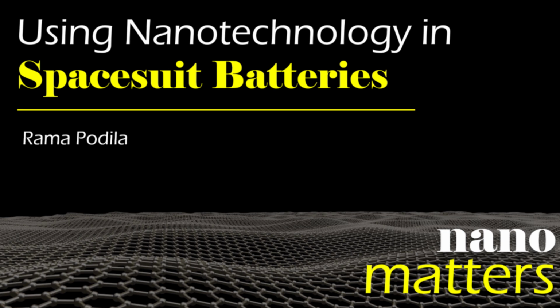So these batteries can not only pack so much power, but they're stable, because now these carbon nanotubes are interlinked between small silicon nanoparticles. So even if they are pulverized, they still fall back within this foam of carbon nanotubes, and they're still electrically connected. And that's how we use nanotechnology to address the challenge with silicon anode, to pack more energy per gram of material.